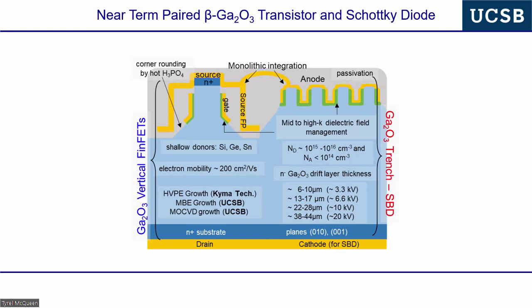So silicon or germanium or tin in the donor case, and they go on one of the two gallium sites. So part of the question is, have you ever done a crystallographic study to see which site is actually preferred, and how they either order or disorder, and to what extent, from silicon to tin? You said the DFT predicts either one or both. And could you actually get a numerical value for what you expect the bandgap to be for a certain donor level, rather than some distribution based off of DFT?